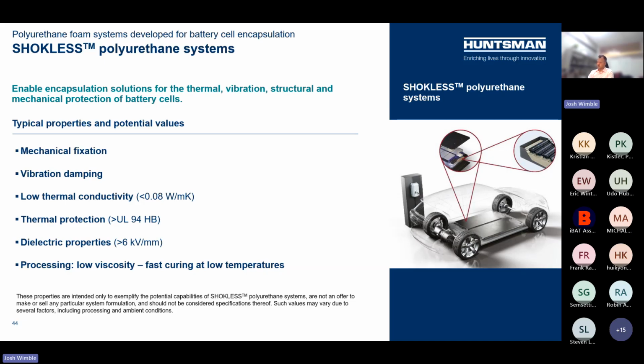So we have a broad range of systems. If you're interested in seeing some of the available systems we have, please follow up with us. Here, I'll just highlight that most of ours are extremely low thermal conductivity with good dielectric properties above 6 kilovolts per millimeter. Most cure within 20 minutes, 30 minutes at most. And by cure, I mean they're stable and able to be moved or rotated without the resin moving. It's basically formed completely. Clamp time, some might call that cure time.